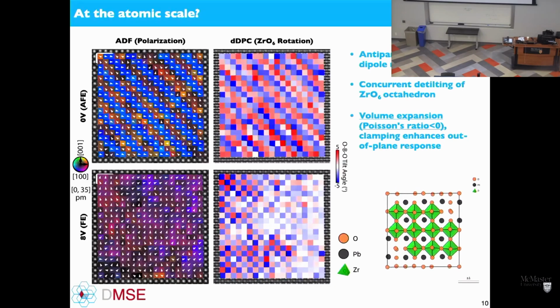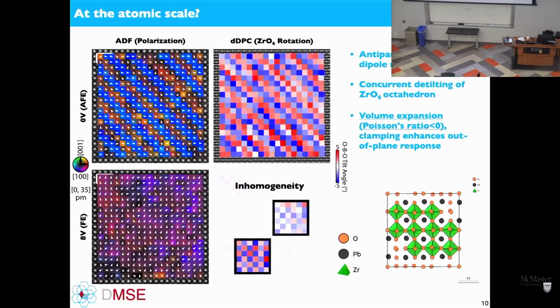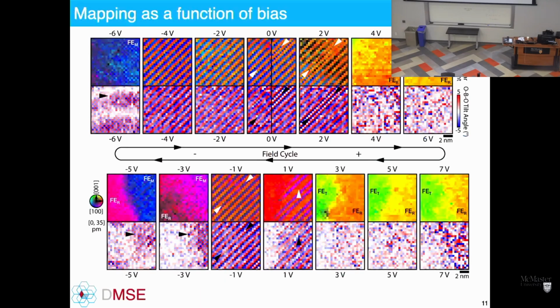But even here, we can start to see how the octahedral tilt changes from zero bias to this high bias, where you're seeing the octahedral oxygen cage rotating as a function of the applied bias that then you can map out. One of the things you notice here is this isn't perfectly uniform. You have inhomogeneity in that transition. And we can do this across the entire voltage range, mapping this out.